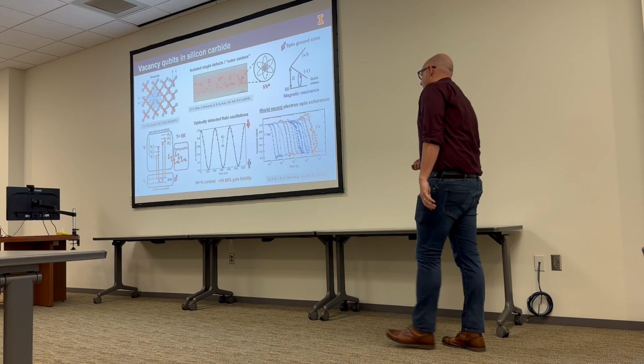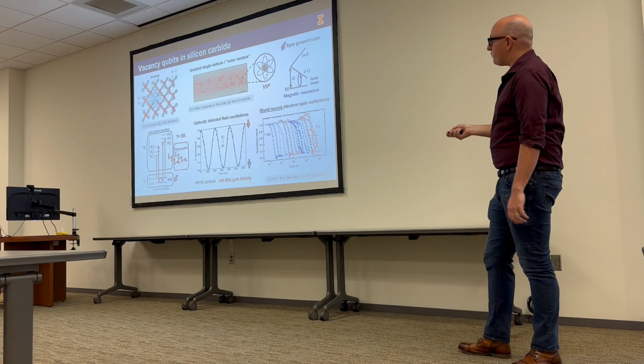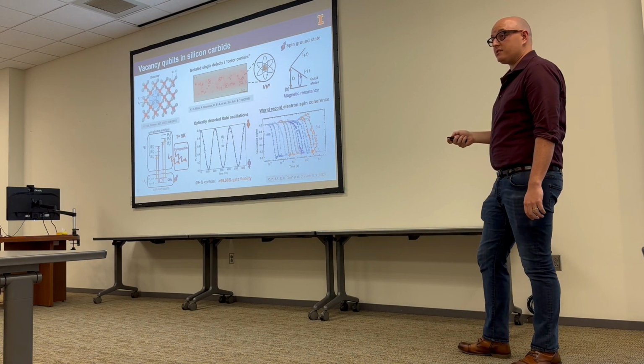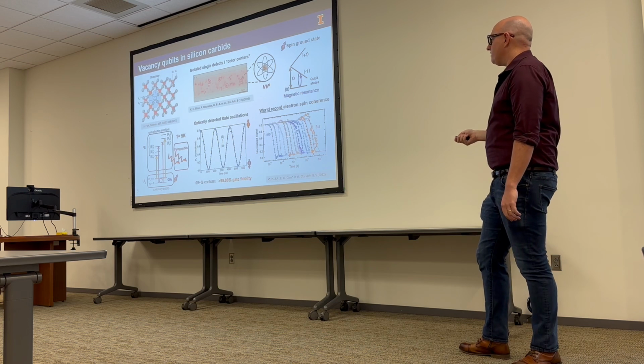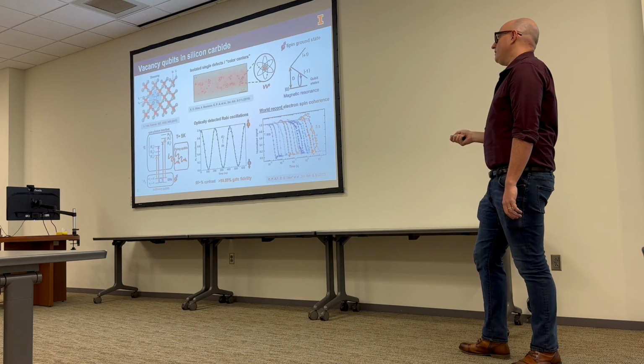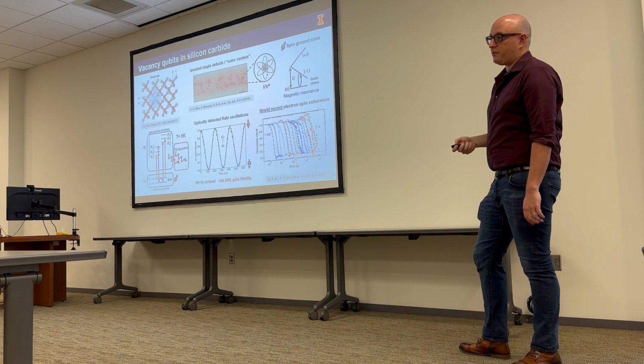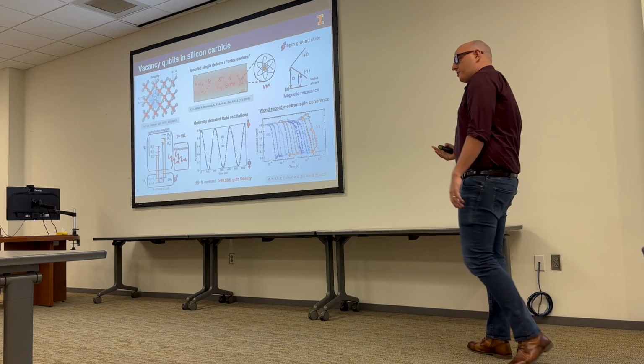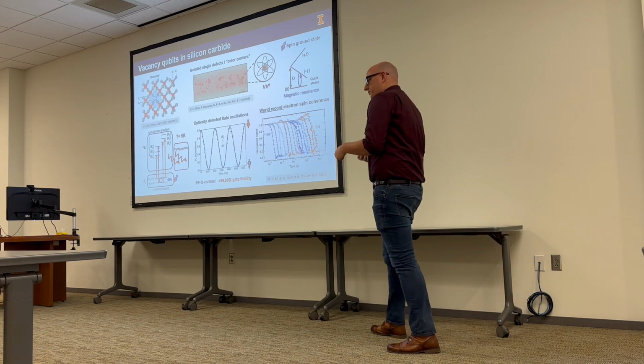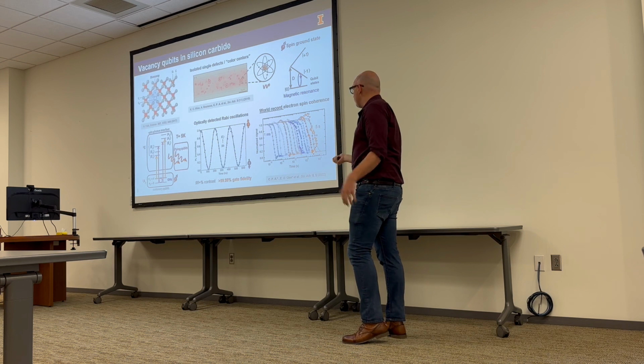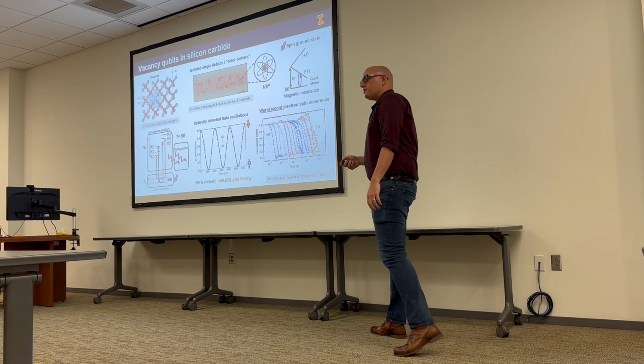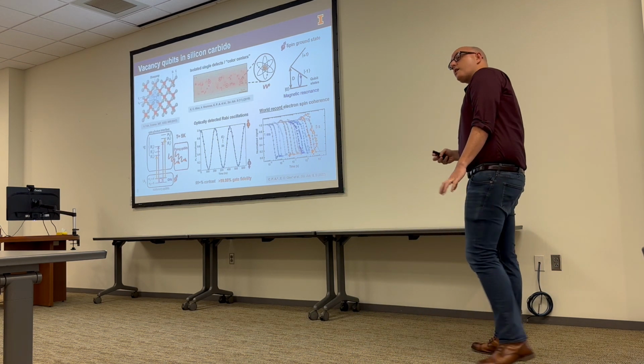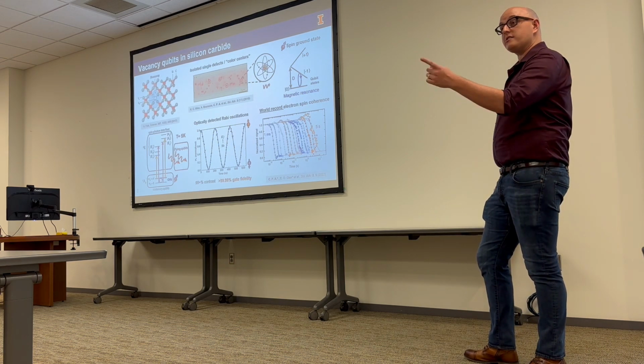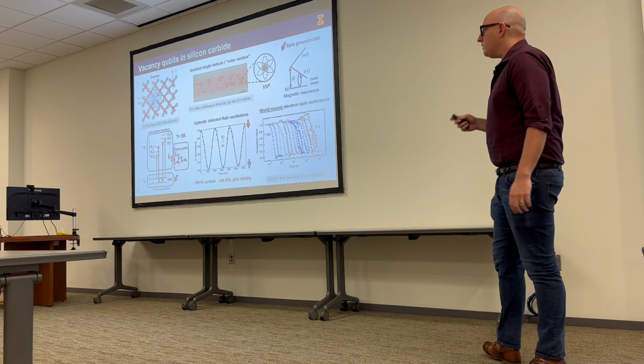And this is the highlight reel. Other things that we've been able to do in this divacancy system in silicon carbide is we recently demonstrated what we think is the world record longest electron spin coherence ever measured in a solid. So basically we have the best electron qubit in a solid that's ever been measured, with a coherence time that's over 5 seconds. And that's an exceptionally long coherence time for these solid state systems. What's the temperature? This is all 5K.